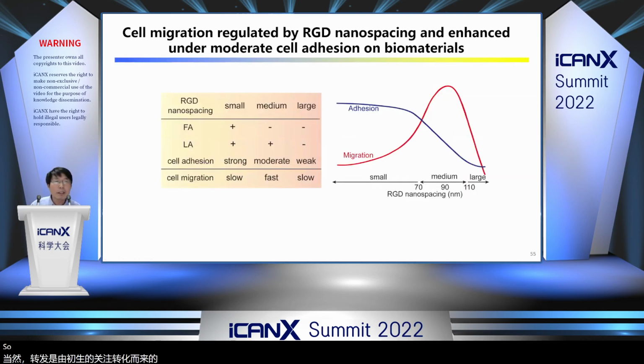So we did a series of cell experiments on a series of RGD nanoarrays. We did find the monotonic change of cell adhesion with RGD nanospacing, and also we found a peak in cell migration. The peak values are dependent upon cell type. However, all these peak values are larger than the critical RGD nanospacing, I mean 70 nanometers. Here is the summary.